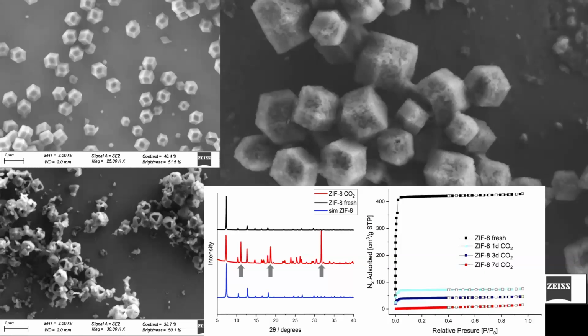Now we are working on improving this, because something that I was astonished by is that if you put a solution of your ZIF-8 as you synthesize it in the incubator of cells, when you remove it, what you have is like a Gruyere MOF. You have a lot of holes inside. We discovered that because in Santiago, it's very humid, and sometimes we forget some samples on the table, and then when we want to see it, suddenly we start seeing cubes with a lot of holes inside. What is this? It was because of the humidity, the CO2 that you have in the atmosphere.